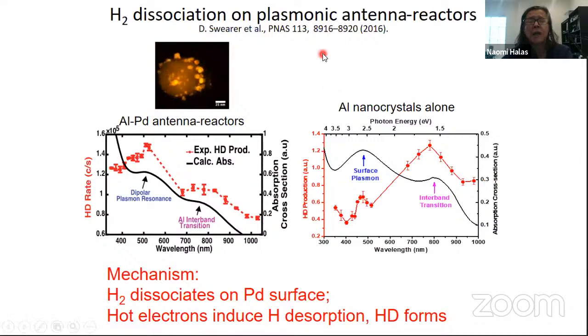So the first reaction that we decided to do involved taking aluminum. There's an aluminum nanocrystal here, and putting small palladium islands on its surface. So here we have the aluminum as the antenna and palladium as the reactor. And so if we try to do the exact same experiment that I showed you a minute ago, just using the H2D2 experiment, and we try to do this with this island structure, we find that when we have an antenna reactor, we have about 50 times greater rate of H2 dissociation than we do when we have just pristine aluminum nanocrystals, which is the data that I showed you a few minutes ago.